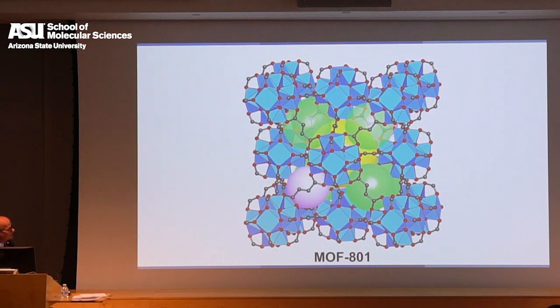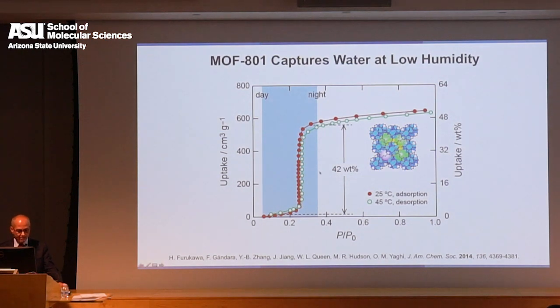The way we discovered this is that we were studying the interaction of water with MOFs as part of the CO2 capture problem. And we discovered this MOF to have this incredible behavior when exposed to water. It takes up water at 20% relative humidity, and it takes it up in a step. And so that means for me to take the water out, I can have a very high working capacity because of the step. If this was shallow, your working capacity would be very low and would require more energy. So we discovered that you can take the water out at 45 degrees, which, having been born and raised in a desert environment, is the temperature the day could go up to. So that gave me the idea that MOFs could be used for harvesting water from desert air.